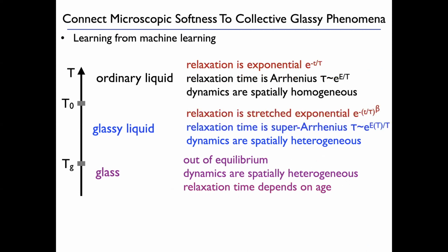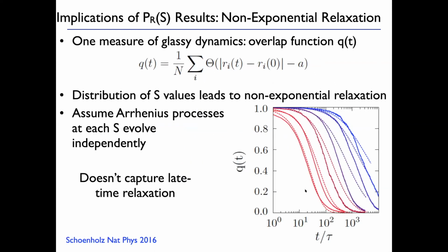Okay, so that works. So the last thing I want to talk about, how am I doing on time, is that the relaxation is exponential above the onset temperature. It becomes stretched exponential below, as I showed you before. Can we understand that? So one way to measure that is to look at what's called the overlap function. I look at all of the particles, and if their displacement in a given interval of time is bigger than some amount, a, which is typically like half the particle size, then they don't contribute anything. But if they haven't moved, then it's 1. So this just counts the fraction of particles that haven't moved in a given interval of time.